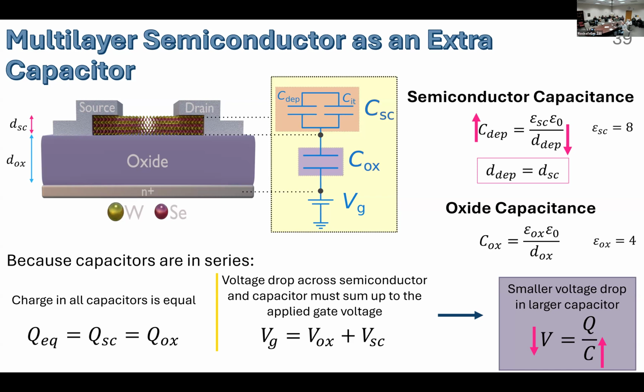So because the semiconductor capacitance for thinner devices is much larger than that of the oxide capacitance, we will experience a much smaller potential drop across the thinner flakes, meaning that we need to apply a higher gate voltage in order to see them turn on. Hence why we have an increase in the threshold voltage for thin devices and a decrease in the threshold voltage for thick devices.